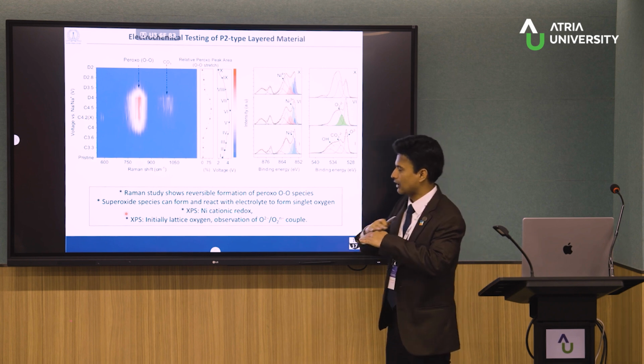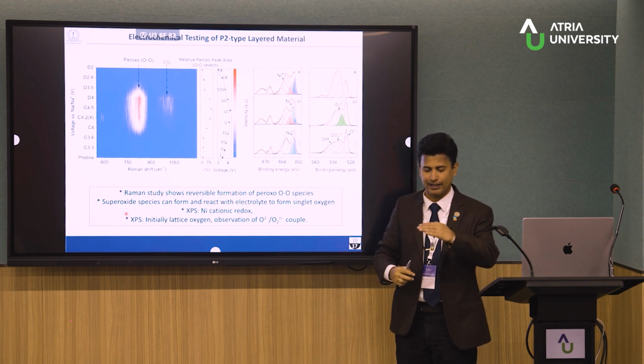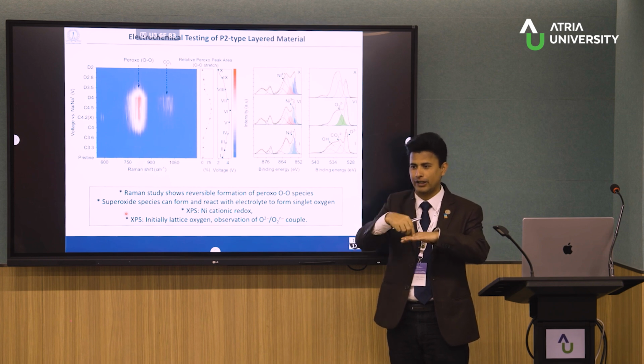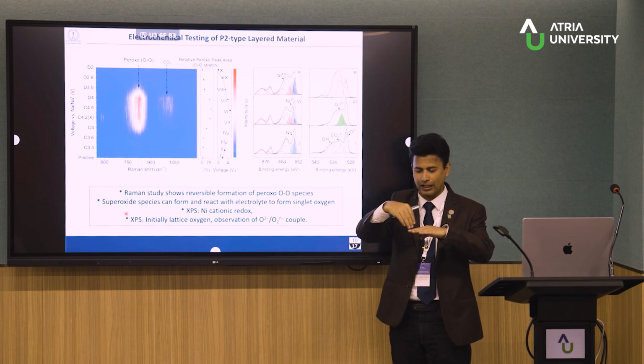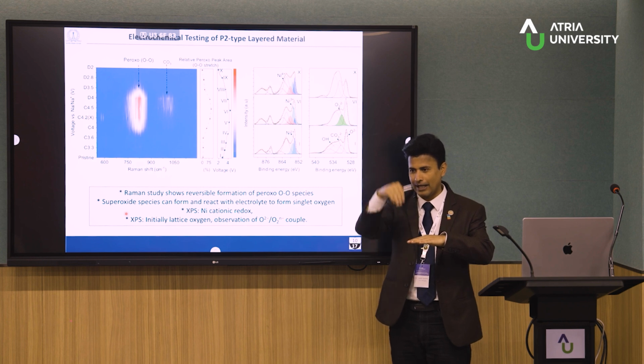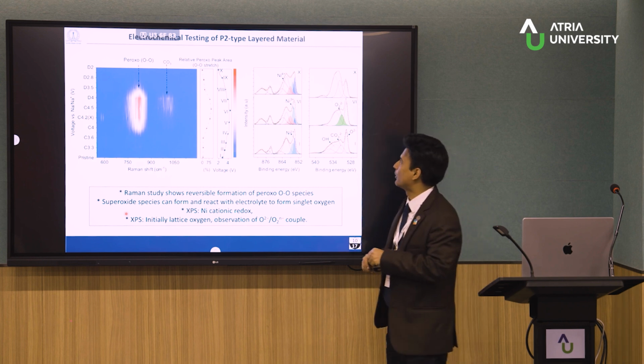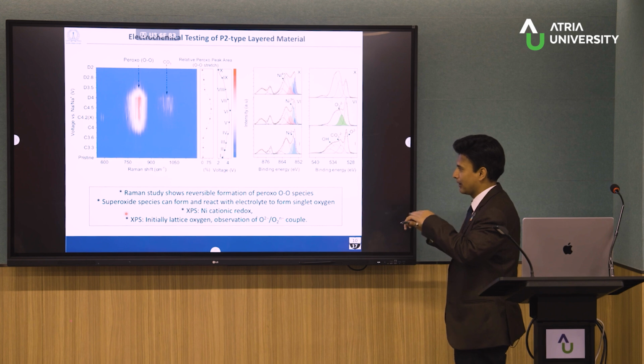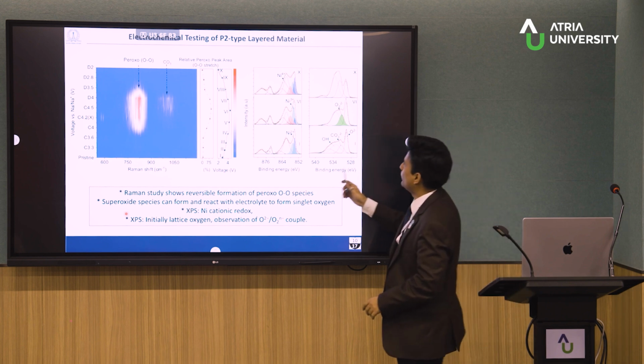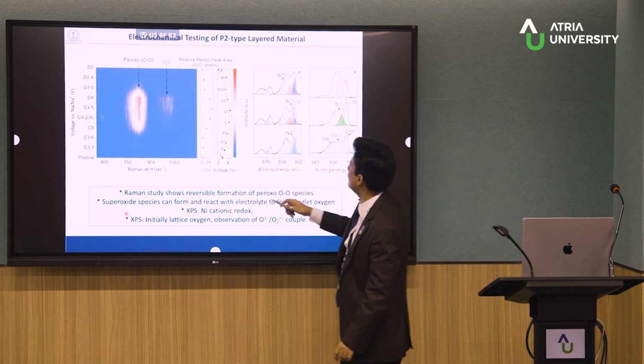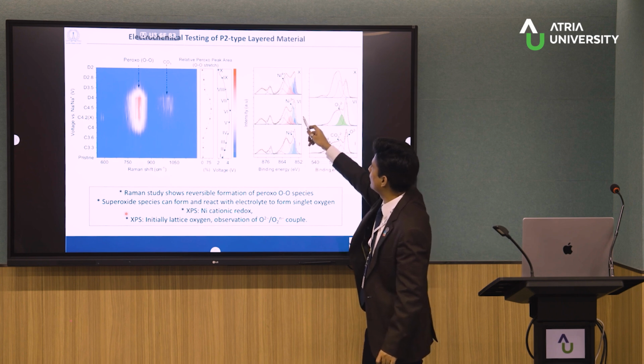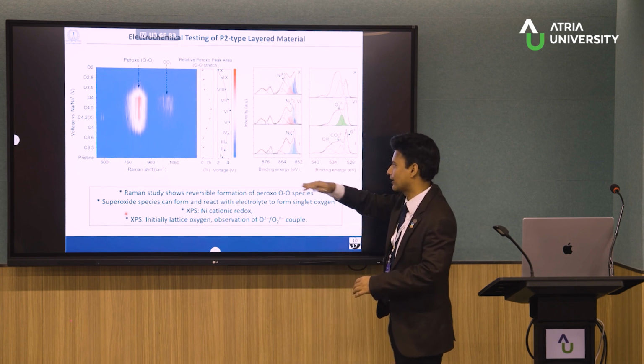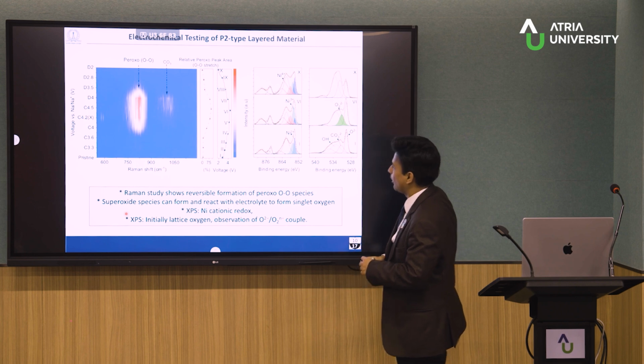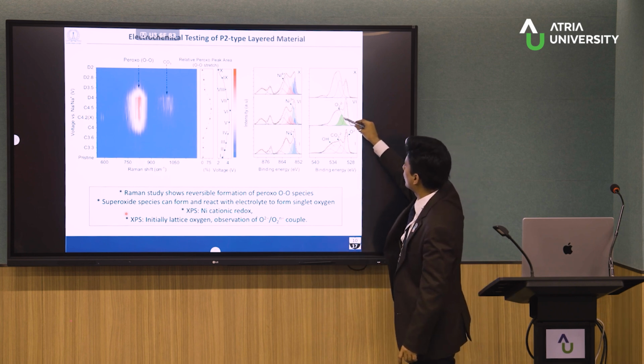Now the XPS is a surface technique, but in IISc we have the machines where we can etch it and do XPS, again etch it further, do it, so it's kind of 50 nanometers something you can etch and you can probe the bulk also. So after about 100 nanometer etching something, when we do that, then we can see during the charging and discharging, we see the typical nickel 2 plus, 3 plus, 4 plus, the nickel redox, cationic redox. In addition, also we see the oxygen redox here.